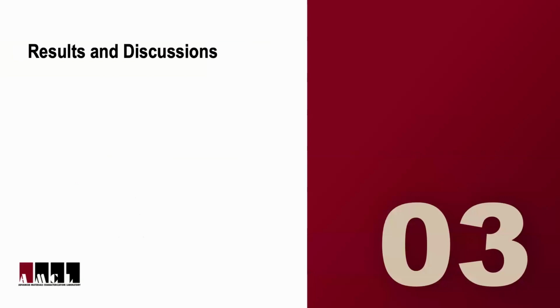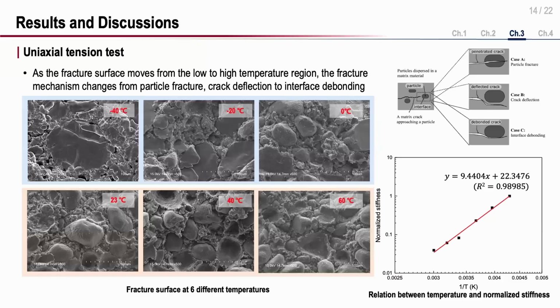And from now on, I'm going to talk about results and discussions. After we conducted the uniaxial tension test, we observed the fracture surfaces for each temperature. And as you can see through these images, we found that as the fracture surface moves from low to high temperature region, the fracture mechanism changes from particle fracture and crack deflection to interface debonding. And this result is the relation between temperature and normalized stiffness, and this result was used to define interface properties for each temperature.